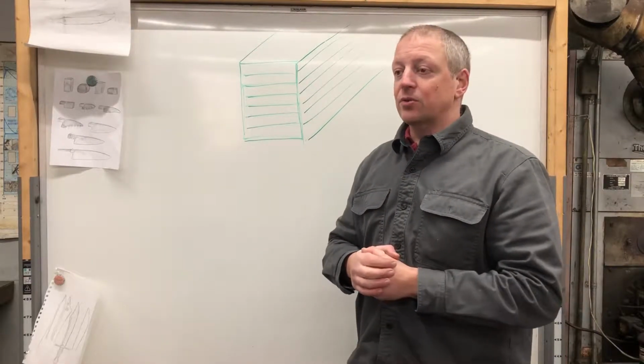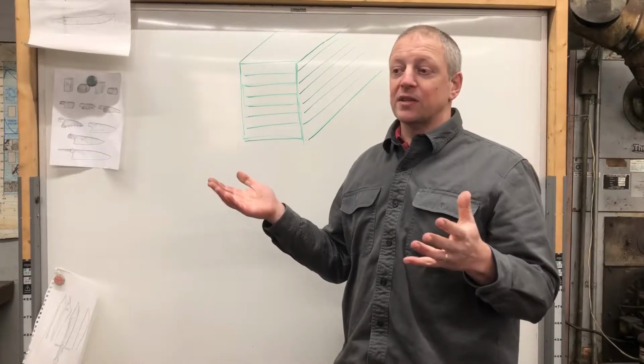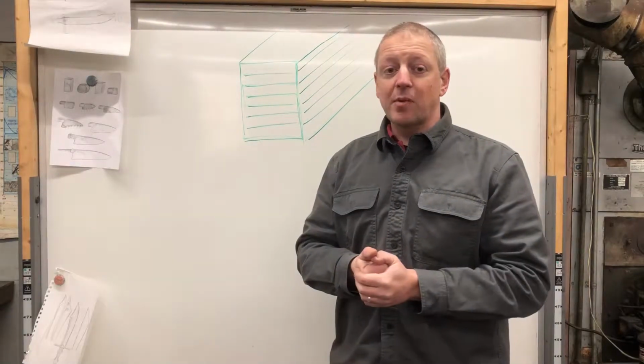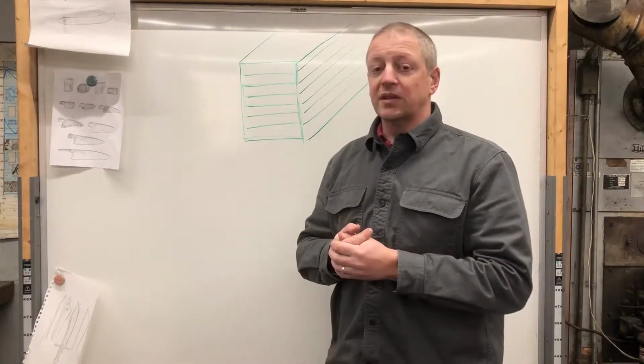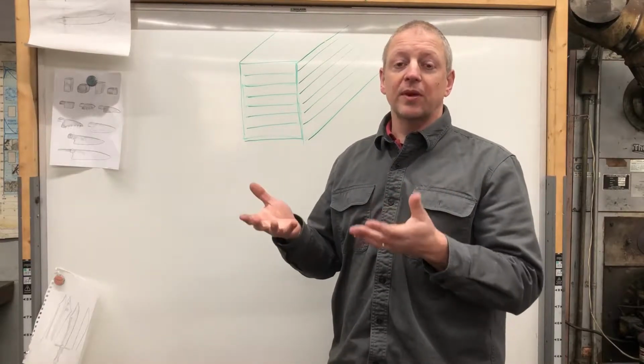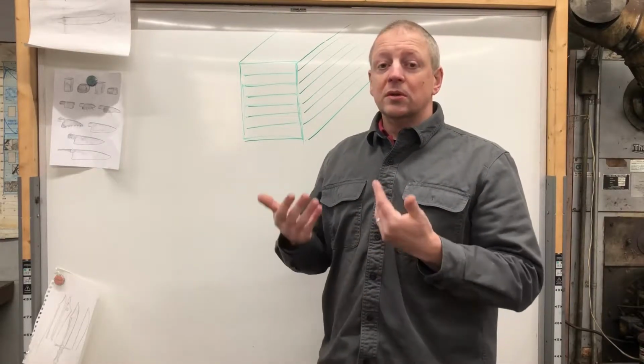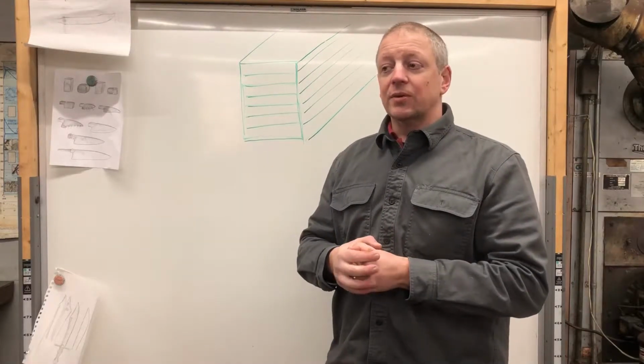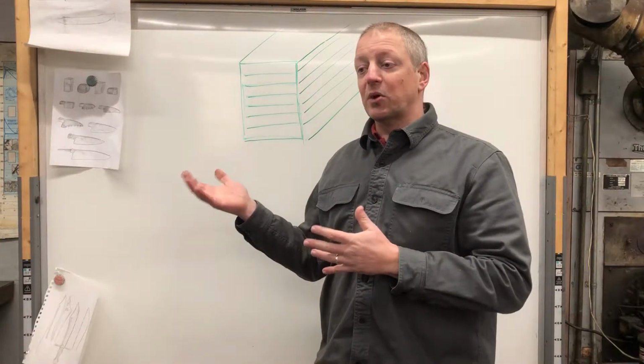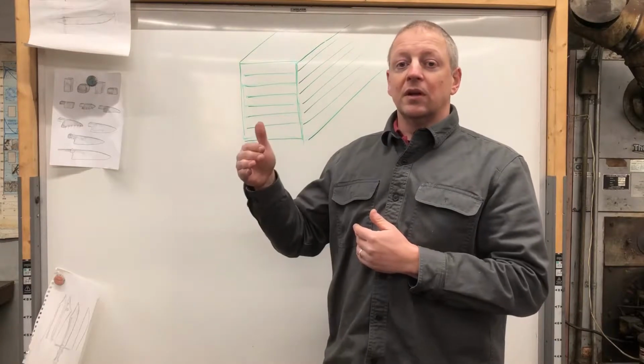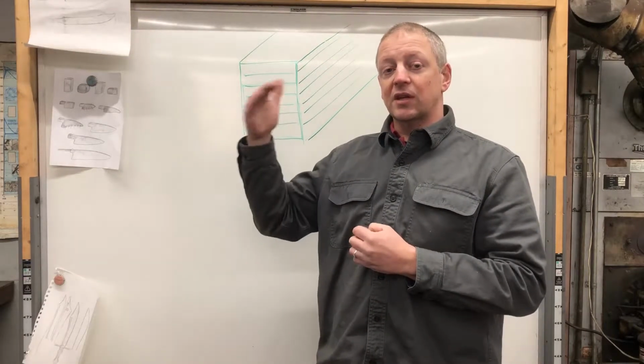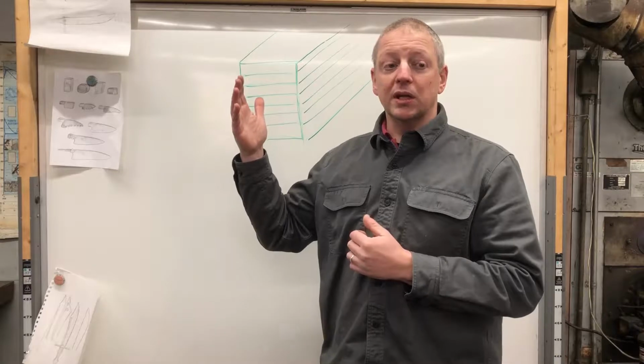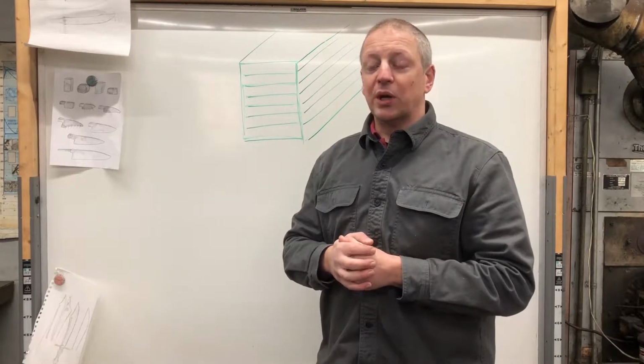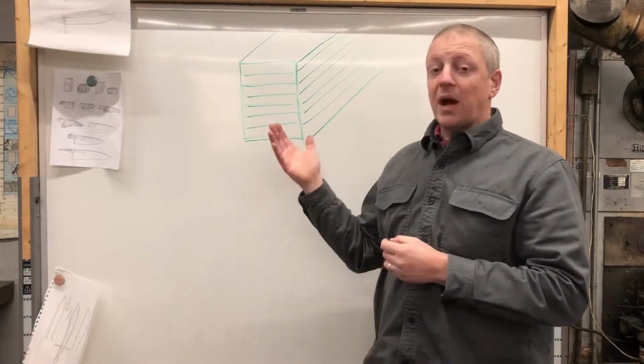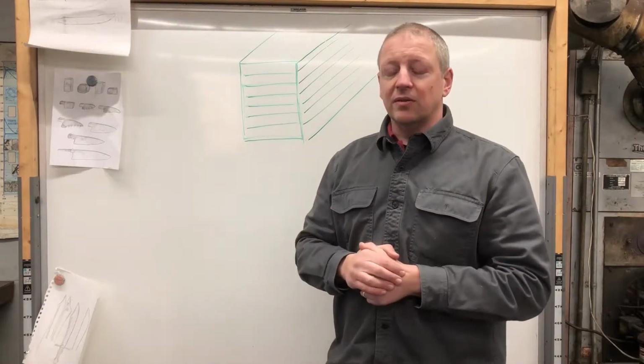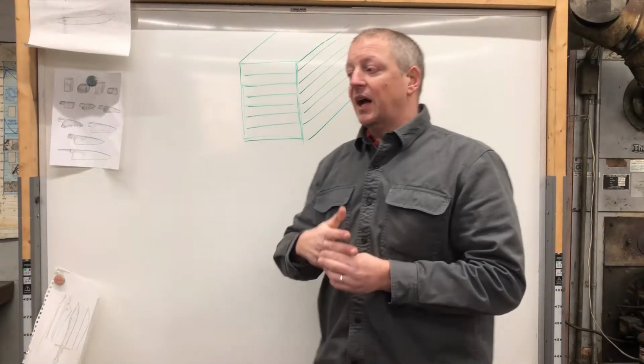Putting your billet into a hot forge, depending on the size of the billet, might take 5 minutes to come up to temperature, might take 10 minutes, whatever it is. You really want this to come up to a nice yellow. Most of this welding should be done at 2200 degrees and hotter. Obviously, you don't want sparkling. You don't want to start burning your steel. But within reason, hotter is better.